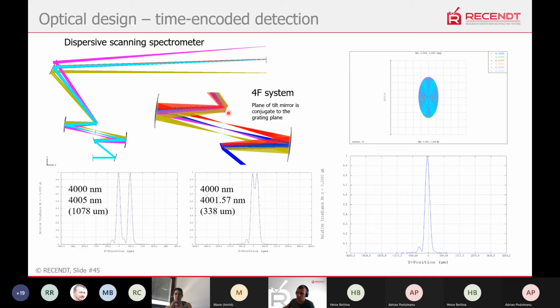So the idea is that it can actually be done quite fast enough for mid-infrared OCT, of course. And it's a kind of kinetic system. In contrast to these reports I mentioned with polygons, we put this system at the end for detection, not for illumination, because you can employ a similar design to make a kinetic source, which was done actually before with lens optics. But since we switched to mirrors here because of the mid-infrared, the beam here is quite aberrated already. It's elliptical. Of course, it can be corrected, but the reasonable solution was to make it as a detection system.